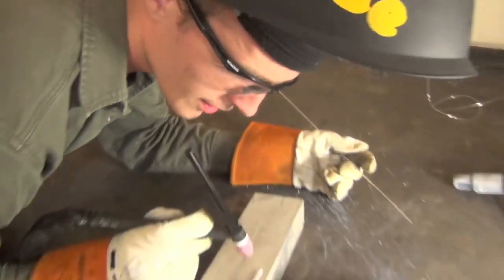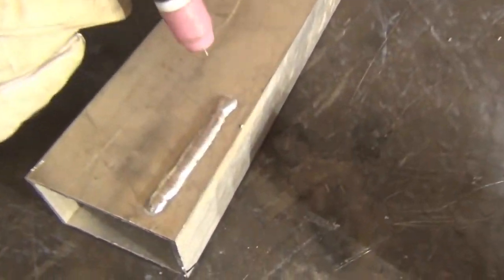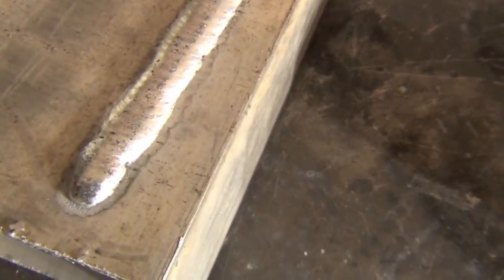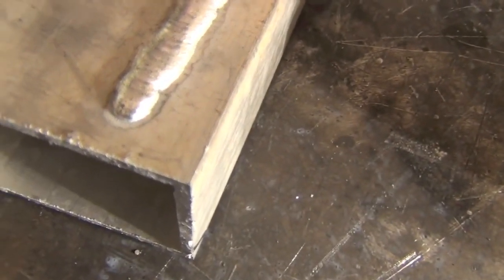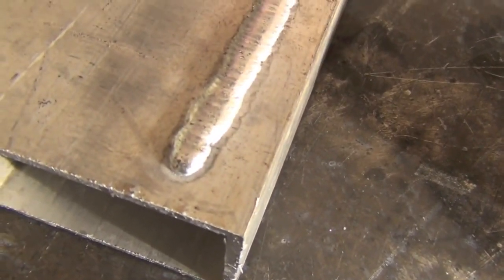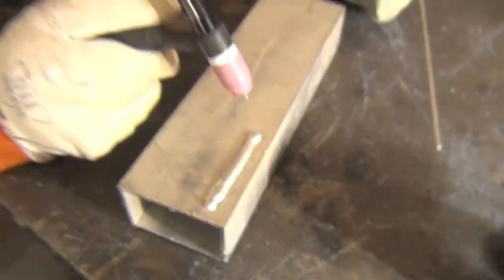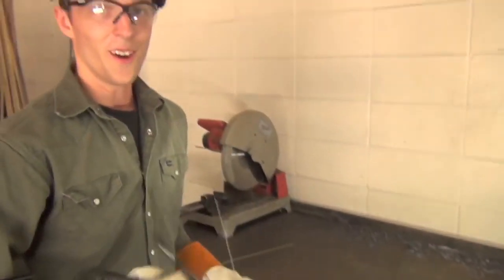Alright, and there's your aluminum TIG weld. Now we do have a little bit of crap on here because we're not exactly working with clean material. But as you can see, every time I dip the filler rod in, we got one of these nice ripples going on. And pretty much I just started back here, ran along, and was able to taper down the current to minimize the crater and pinhole at the end. So, that and all of its awesomeness is AC TIG on aluminum.